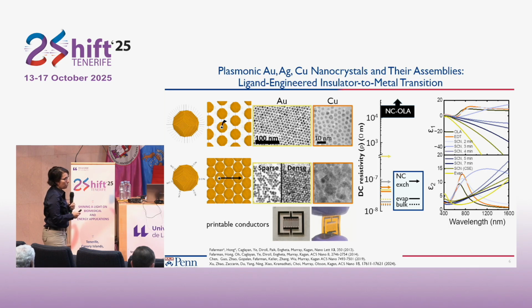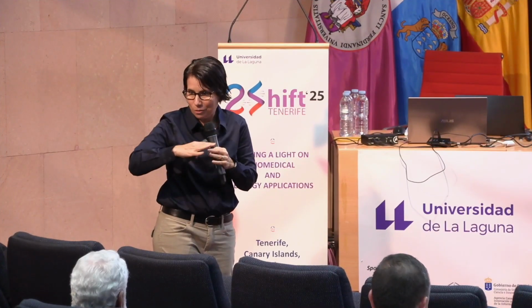And if we use some of these compact inorganic ligands, the particles become much closer together. And depending upon the material that we make them from, in some cases, they just bring them close together. In some cases, particles will actually start to fuse together. And in other cases, they'll really grow into grains.